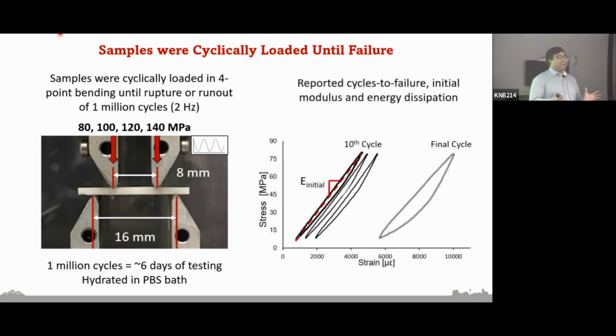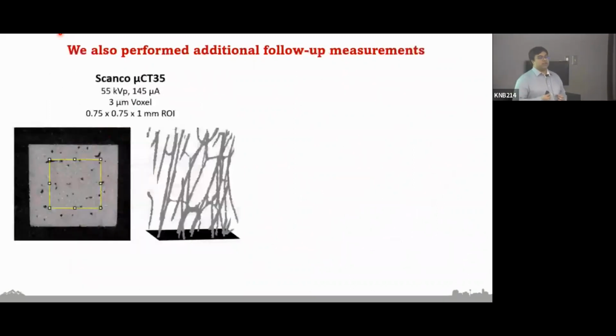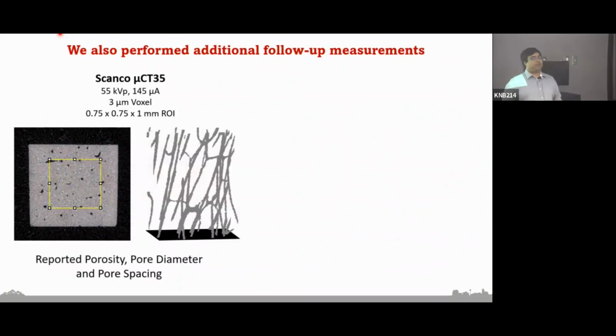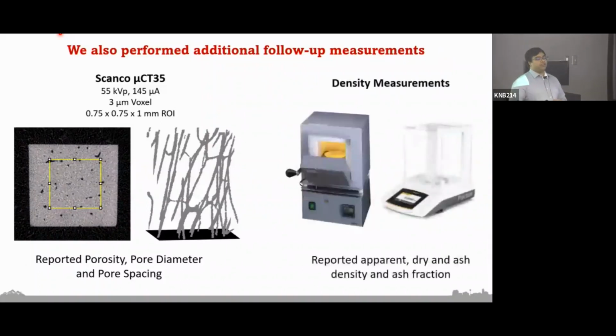So in addition to recording the number of cycles to failure, we were also able to track the stress and strain across the cycles. From that, we got some biomechanical measurements like stiffness and the total energy dissipated as part of this failure process. In addition to that, as I mentioned earlier, we did some micro CT. For this study, I developed some custom code that let us automatically identify the pore space. Then I got to use a workflow that was developed by Lindsay Lowndegan for her PhD work that quantified the porosity and things like the pore diameter and the pore spacing. Since we had little pieces of bone, we were also able to take some manual density measurements, just with calipers and scales, and we even had a little oven, so we were able to separately quantify the apparent, the dry, and the ash density of these bones.